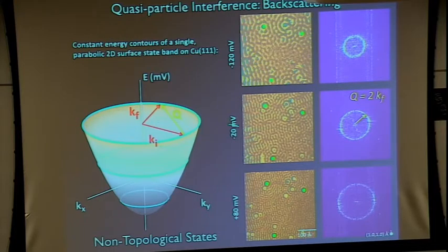But the 2kF wave vector, if you look at the scale, the susceptibility there is the largest. All of it is possible. Okay, and that's basically what this experiment measures. I'll show you lots of examples of this, and there are many ways to analyze this information. You can start with the Green's function and do a T matrix calculation, with your given band structure, and I'll show you some examples of that, and compute what the STM should measure. That's one approach you can take.